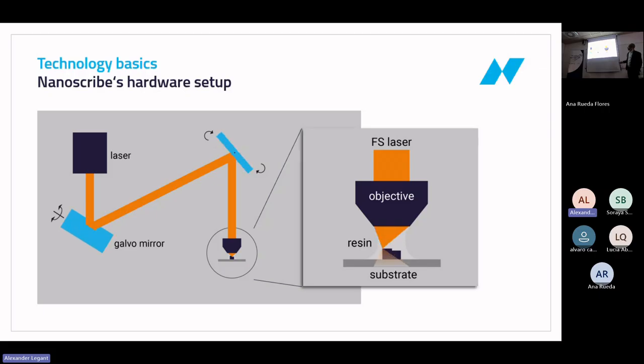And by now moving, using two coupled galvo scanners, we can just scan along one layer. Then afterwards, we move in X, Y, and Z to expose one area after the other. Afterwards, the sample is removed from the system, put into a washing bath, monomers are washed out, and you have at the end your freestanding sample, with some examples of what you saw before.